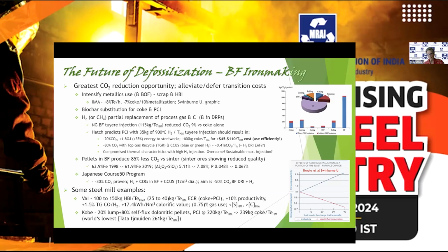At the bottom there, Kobe Steel has reached a record for coke at 239 kilograms of coke per ton of hot metal by using 20% lump, 80% self-fluxed dolomitic pellets and PCI at 220 kilograms per ton of hot metal.